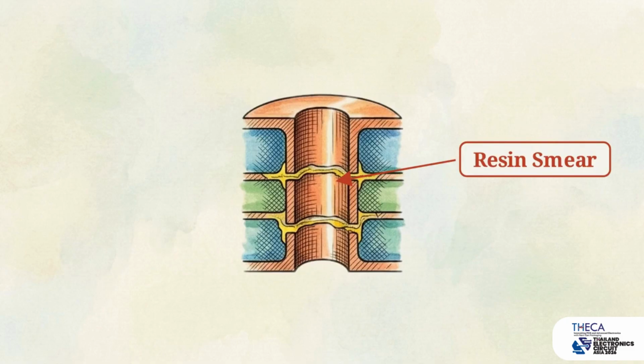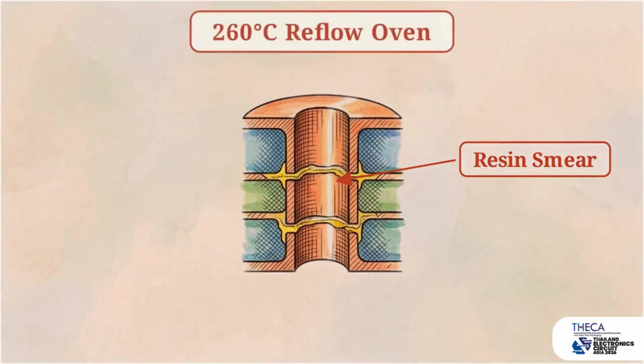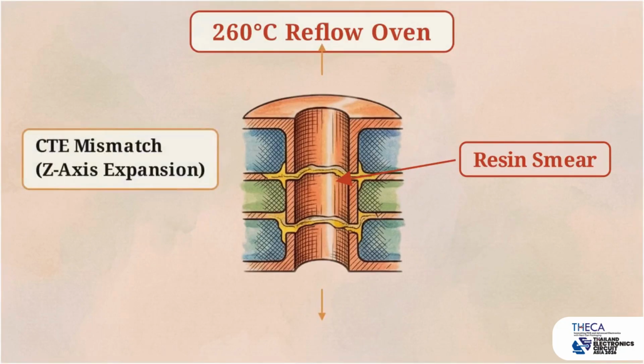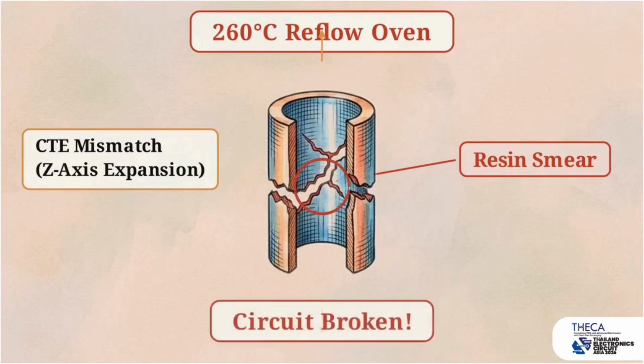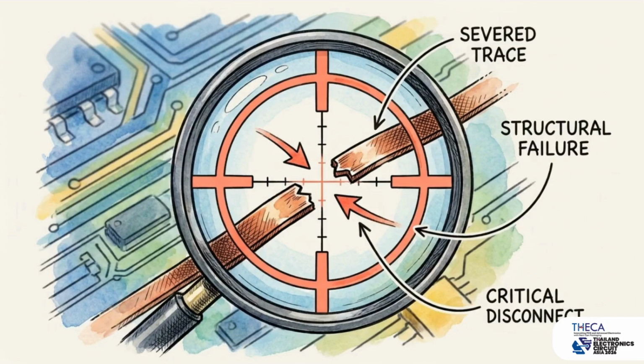When this weakened via hits the 260-degree heat of the reflow oven, physics take over. The FR4 expands aggressively along the vertical z-axis, exerting massive mechanical pull on the rigid copper barrel until the resin-smeared joint violently separates, completely breaking the circuit. Engineers classify this specific structural failure as an interconnect defect.